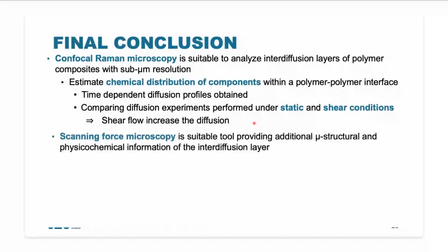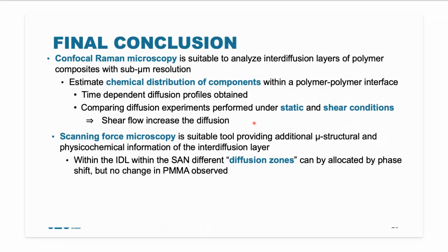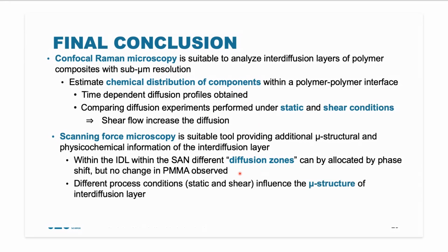As the complementary technique, we use scanning force microscopy, which is a suitable tool to provide additional microstructural and physical-chemical information about the interdiffusion layer, which allows us to allocate within the SAN region different diffusion zones, and we do not see any mechanical change within the PMMA layer. When we have different process conditions, static and shear, we could also see that the microstructure of the interdiffusion layer has to be changed.